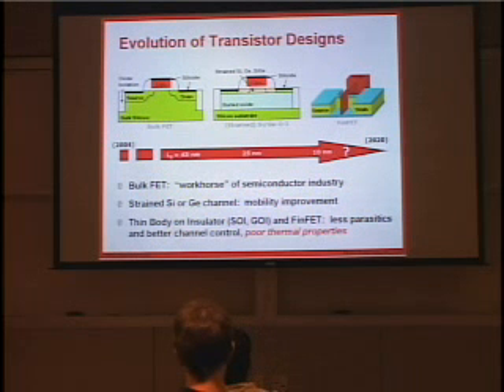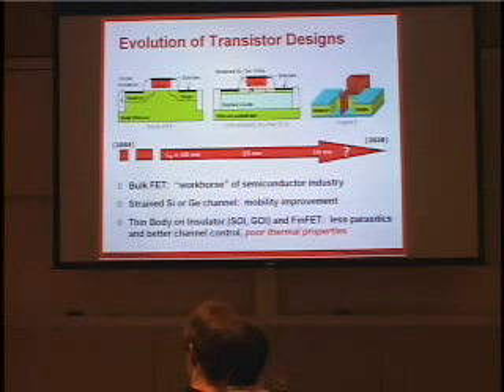That's a little bit more of a research topic. I don't think there are any commercial products using FinFETs yet, and there are no commercial products using germanium on insulator devices. In fact, that's a very, very recent research topic about getting very thin germanium films on insulator and taking advantage of mobility improvement in that. However, what's happening here is that because of the confined geometries and because of the buried oxide that is usually stuck below these transistors, they have much poorer thermal properties than bulk silicon, and that's essentially what I'll be looking at for the rest of this talk.